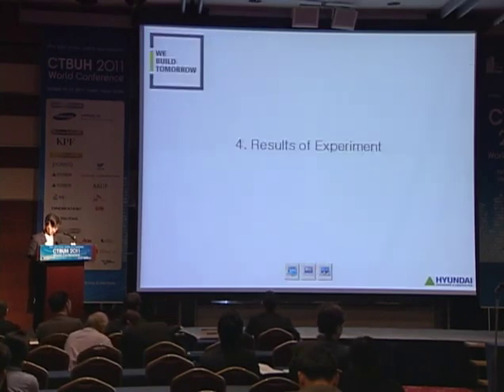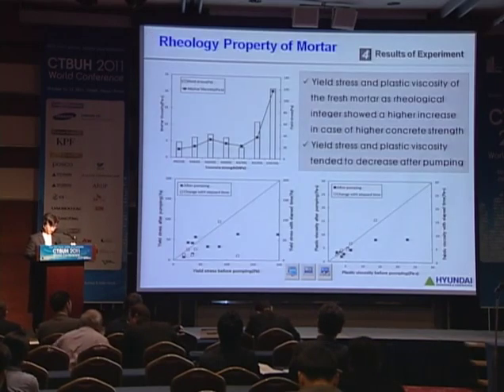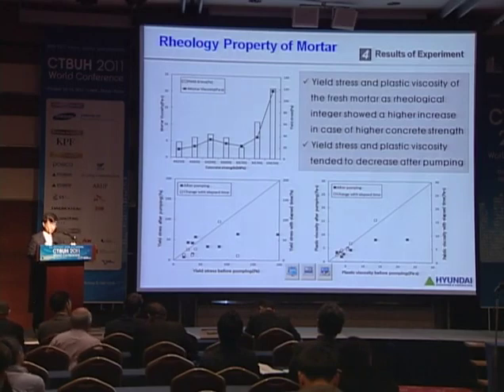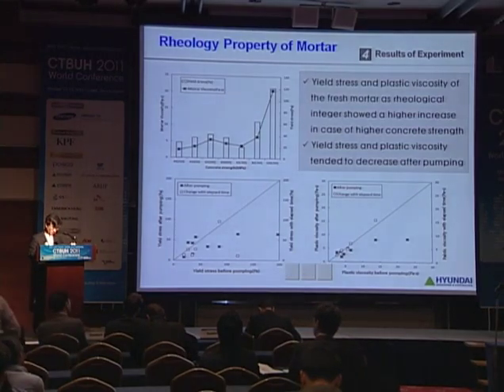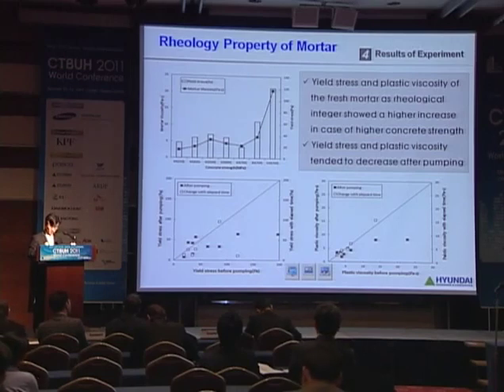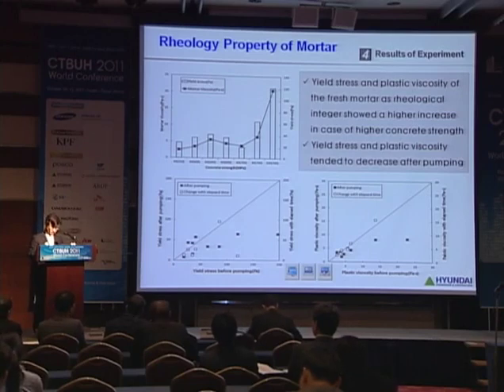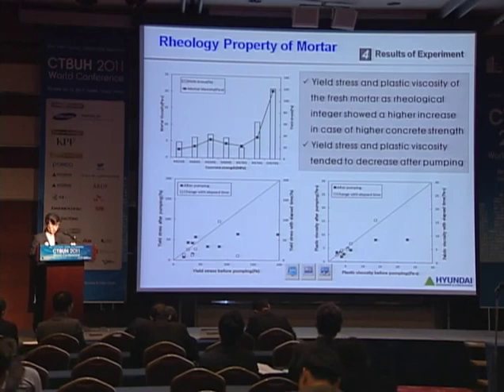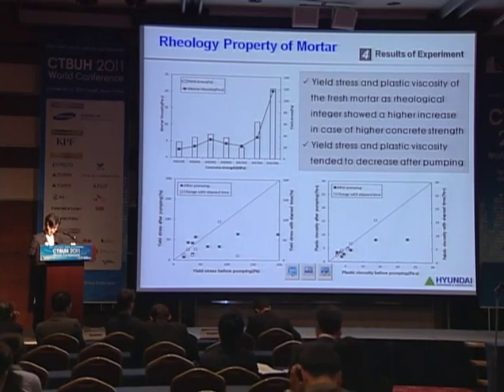The next is results of experiment. First, rheology property of mortar. The upper figure shows the test results of plastic viscosity and yield stress of mortar according to concrete mix conditions. Generally, the higher strength of concrete shows higher plastic viscosity and yield stress. And at the bottom of the picture, the result of measuring rheology before and after pumping shows a general tendency of decrease in yield stress and plastic viscosity after pumping.